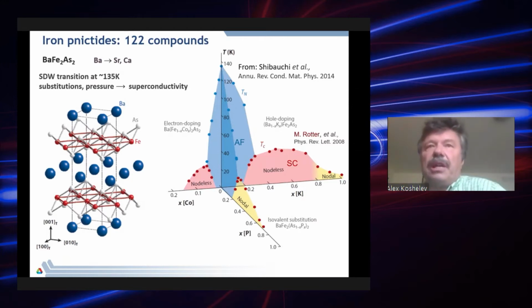So the material which I am going to discuss today is derived from the so-called 122 compounds, which were discovered in the early days of iron-based superconductors. The parent materials are not superconducting. They have a spin density wave transition at 130, for this material 135 Kelvin, but superconductivity may be induced either by random substitution or pressure. There are many substitutions which eventually suppress the spin density wave state and produce superconductivity. This has become a big field by itself.